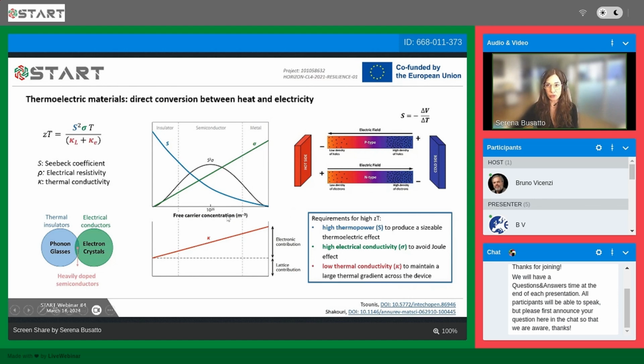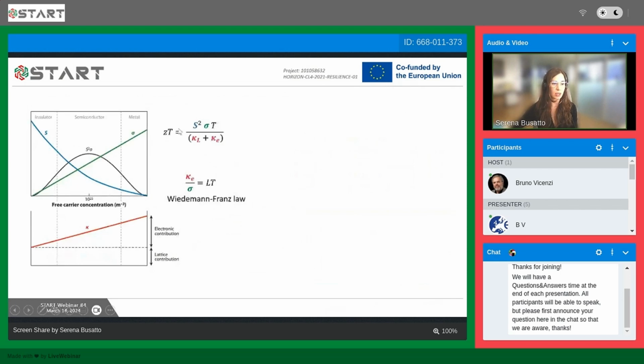But why nanostructuring is so important? It's so important because the thermal conductivity has two contributions. One is from the lattice and one is from the electrons. But the one from the electrons is related to the electronic conductivity by the Wiedemann-Franz law, and therefore it cannot be lowered. So what we need to minimize is the lattice contribution.